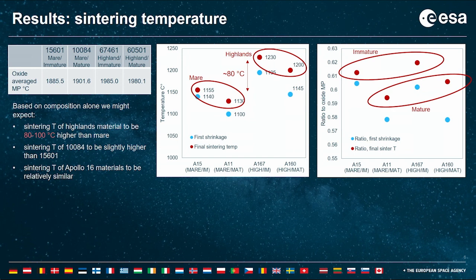So to look at the difference that we see relative to what the composition would predict, we can look at this as a ratio. And here we can really see that the immature material sinters at a higher temperature than the mature material. And the other thing that we can see is that the speed of the sintering, so how rapidly it goes from being lightly sintered to very sintered, is quite different for the materials as well.